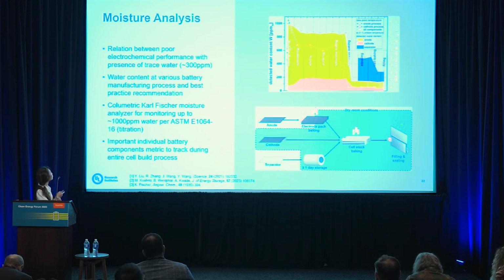The coulometric Karl Fischer moisture analyzer can help to monitor up to about 1,000 ppm of water per the ASTM standard. So it's also an important metric to track, especially for the individual battery components during the entire cell build process.